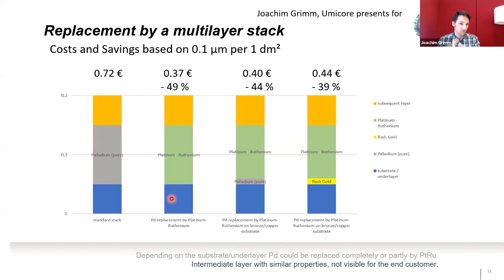All these plating systems in rhodium, ruthenium, platinum are highly acidic. And if you have, for example, not sterling silver, but brass or copper-based materials as your alloy, as your base material substrate, you need something as a barrier so that, while plating, the acid is not attacking your base material. Therefore, you can still do just the flash of the pure palladium. So you keep your palladium, do the flash of it, and then your main intermediate layer you build up with platinum-ruthenium, and then you do your final layer on top. So you can do it even on bronze or copper alloys without an effect to your substrate. And you still have the saving of 44%, as you have to use only a little bit of the expensive palladium.